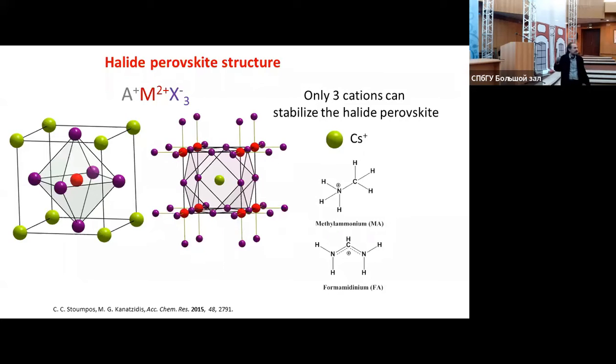So halide perovskites, unlike the oxide perovskites, have a halogen atom in the X position, and this halogen sits in the corner. In the ideal structure, it sits in the corner of a cubic crystal structure with a divalent metal sitting in the middle, and then at the corners of the cube we have the A-site cation, which is basically a non-bonding cation that fills space and balances charges. And you can describe the perovskite either like this or like this. They are equivalent descriptions. But unlike the normal perovskites, you can have a plethora of compositions that you can achieve.